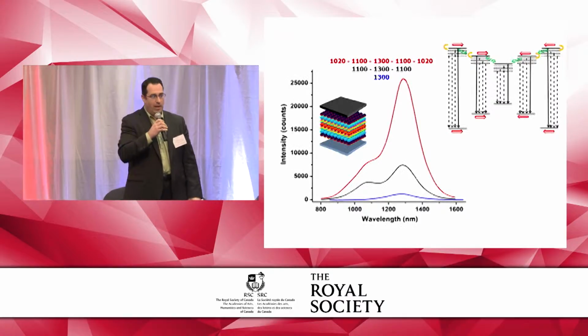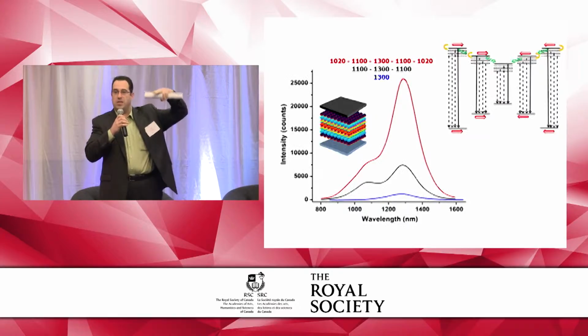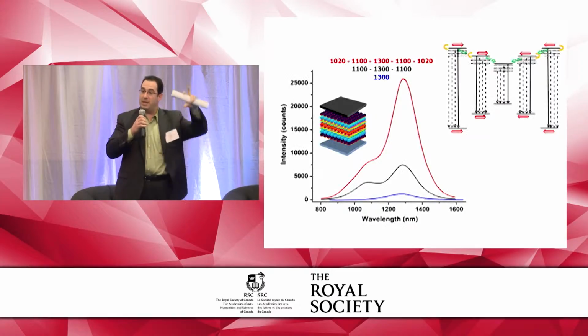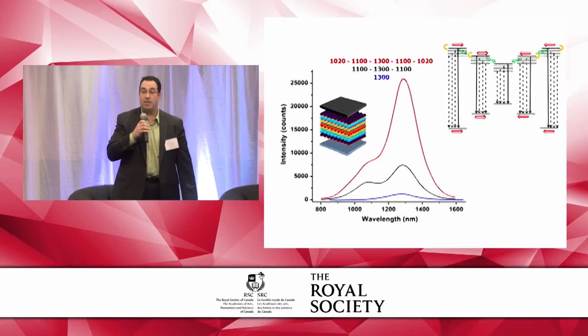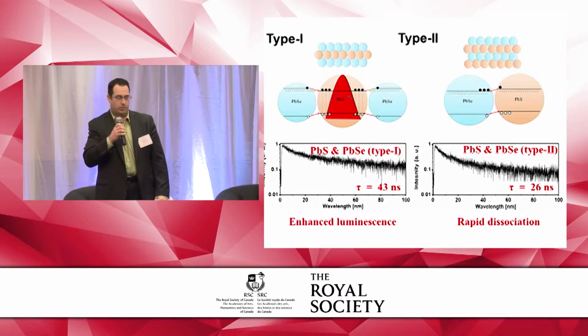So very useful when you want to make devices. The other thing that we found is since we assemble them layer by layer, we can change the size of the nanoparticles as we assemble them, and that allows us to bring the charge to the middle of the film, keep it there, and give much, much, much better performance as far as the material goes.